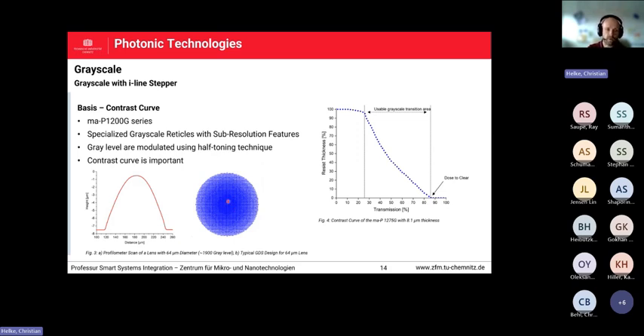And what is also very important, because you need the answer of the photoresist during the dose modulation itself, is to get this into the model for getting all of this layout data for the transmittance curve running, so that you really get the structure you want after the exposure. So this is called the contrast curve. This is shown here on this side, which is very important, because with this you can tune your 3D structure to the right angle or rounding or whatever you want to have at the end. So again, it's like a dose, which was on the slide before, but here it's called transmission.